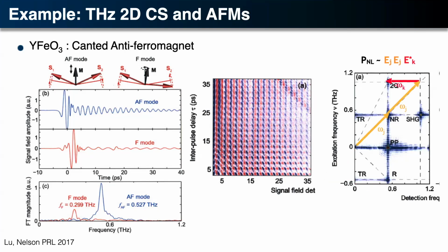That is a response up there, which we call the 2Q, and for this system, which is a magnon system, it corresponds to an excited state with two magnons in it. So it gives you analogous and complementary information to two-magnon Raman. But in two-magnon Raman, you excite zone boundary magnons, and these are zone center.